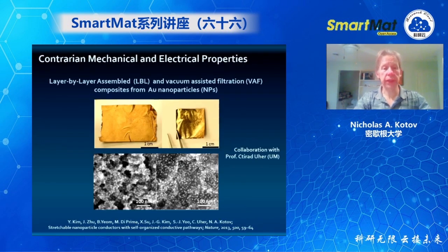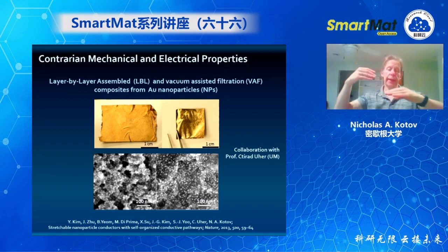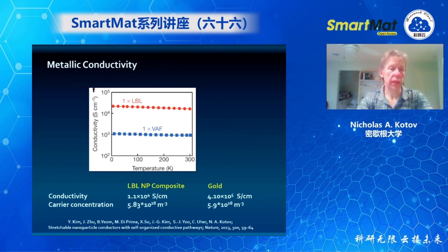And initially, we started with electrical properties. It was done in collaboration with my good colleague at the University of Michigan, Ctirad Uher, and we decided to assemble gold nanoparticles in layer-by-layer fashion so that we allow gold particles to assemble at each interface into chains. And this resulted immediately in something quite unique. The conductivity of these composites was extremely high.